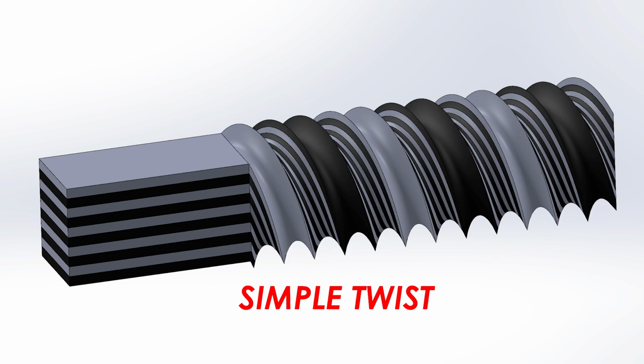I am twisting only one section of the billet so you can see the straight laminate on the left-hand side. The billet is twisted 3 times. That means 3 times 360 degrees of rotation, which generates 12 visible loops. 1 loop for each side of the billet, which has 4 sides. You immediately realize that this does not look like our blade's pattern. There are too many layers to start with, and also a large black loop that does not appear in the original.